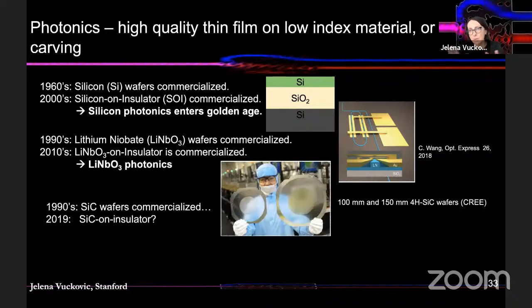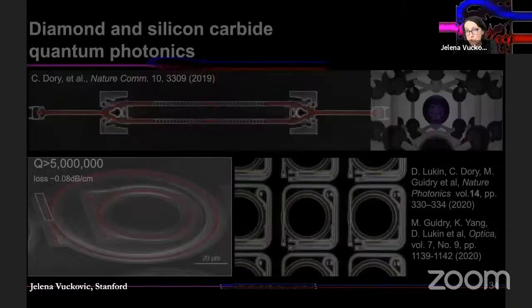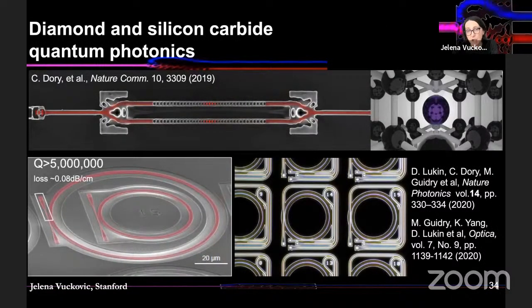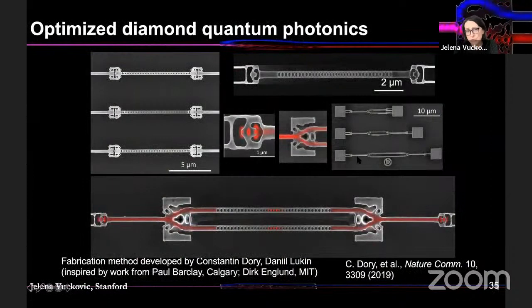But for silicon carbide, you can only get 6-inch or 4-inch bulk wafers. There is no thin film silicon carbide on insulator. Now, some companies are actually planning to launch it, but as of now you can't really get it commercially, which is why we had to make it ourselves. And I'll show you in a moment how we're doing it. For diamond, we also had to figure out how to make guiding structures, which we're doing by 3-dimensional bulk carving. So these are some examples of diamond and silicon carbide structures we make, and you can also see all these inverse design elements that are already implemented there.